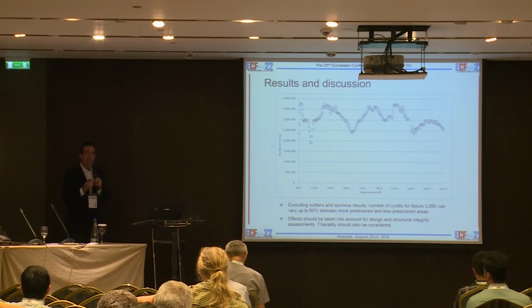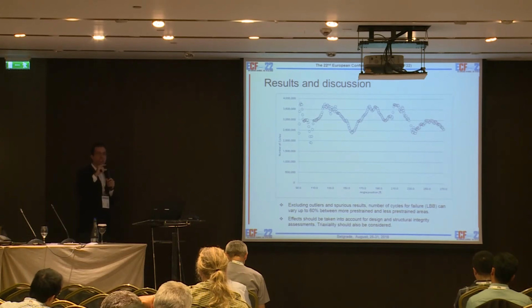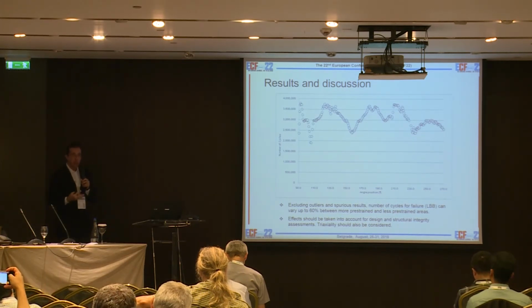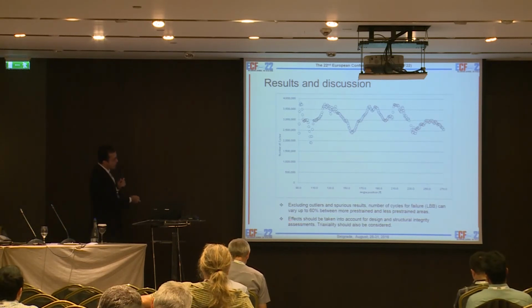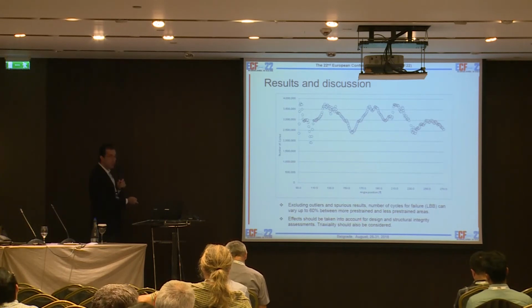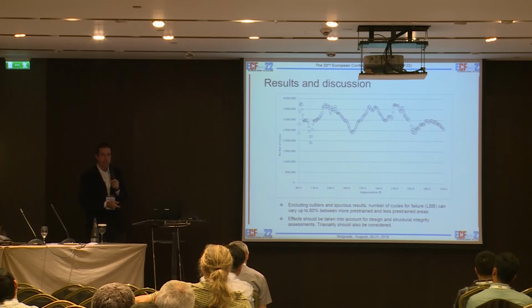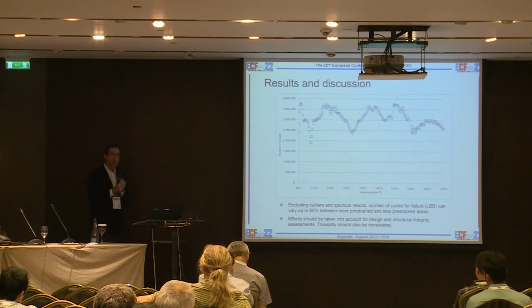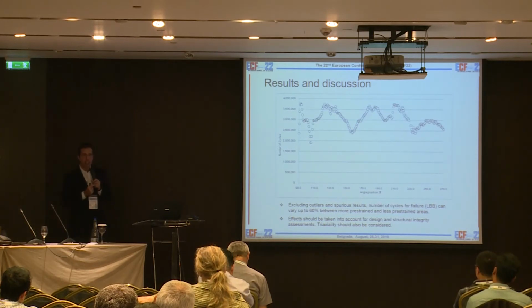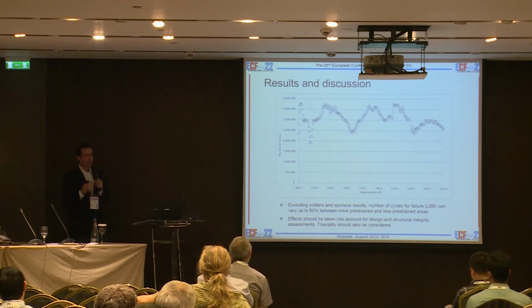So this is the main reason why, in our case, we were not succeeding in validating experimental data. When we started considering such phenomena, the results started to converge, and we had much better coherence. And we consider that such effects should be taken into account, both for design and structural integrity assessment. And I have one extra suggestion. We did not show here the inclusion of triaxiality in the fatigue crack growth calculation, but I suggest that it's also included because we have another investigation running in our lab in which stress triaxiality plays a relevant, remarkable role.